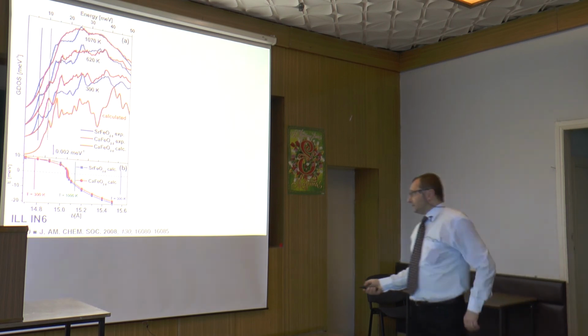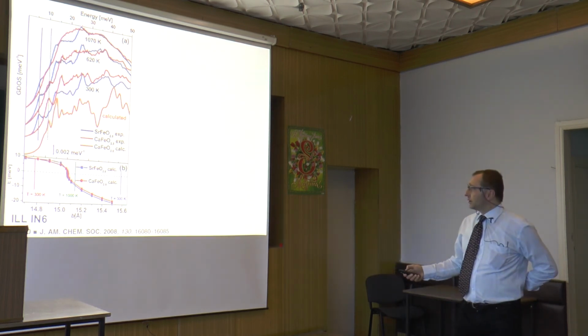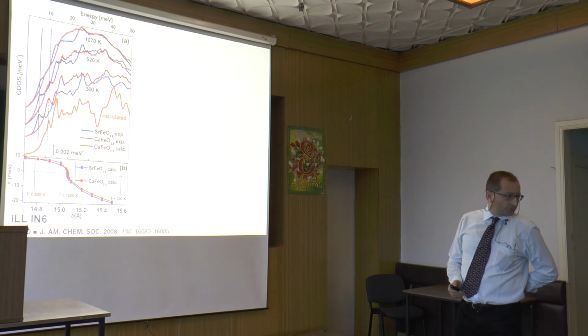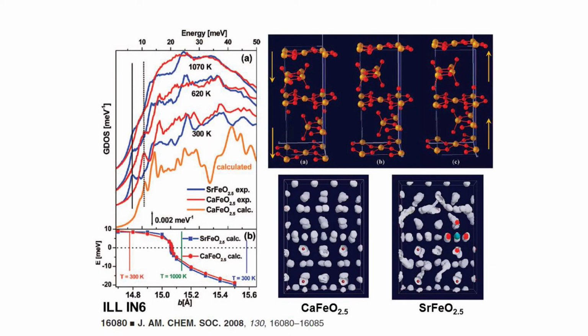These are ab initio calculations that show the energy position of this soft mode. What is important is that these are ab initio calculations where we do not optimize the cell. We fix the lattice parameter B, which is a very important parameter. So we fix it, we don't optimize it. Let's imagine that the lattice parameter is 14.6, and then make the ab initio calculation. And then we see that basically the fact that we have strontium or calcium does not affect the energy of these soft phonon modes. Okay?